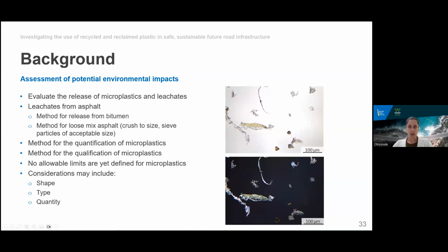Therefore, in this section, we include the methods we used for the assessment of leachates and microplastics, where we tried 3 different methods to measure leachates, one assessing the binders before mixing with aggregates, and a couple using the loose asphalt mix. One where we crushed the coated aggregates to size, and another where we selected only the appropriate sized aggregates without crushing them. As far as microplastics were concerned, we considered methods for both their qualification and their quantification.